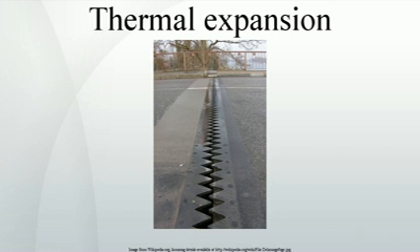Contraction effects. A number of materials contract on heating within certain temperature ranges. This is usually called negative thermal expansion, rather than thermal contraction. For example, the coefficient of thermal expansion of water drops to zero as it is cooled to 3.983 degC and then becomes negative below this temperature. This means that water has a maximum density at this temperature, and this leads to bodies of water maintaining this temperature at their lower depths during extended periods of sub-zero weather. Also, fairly pure silicon has a negative coefficient of thermal expansion for temperatures between about 18 and 120 Kelvin.